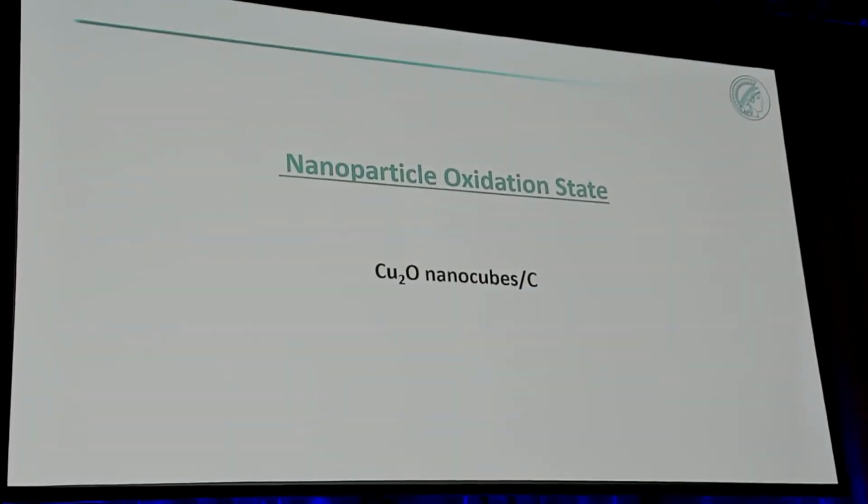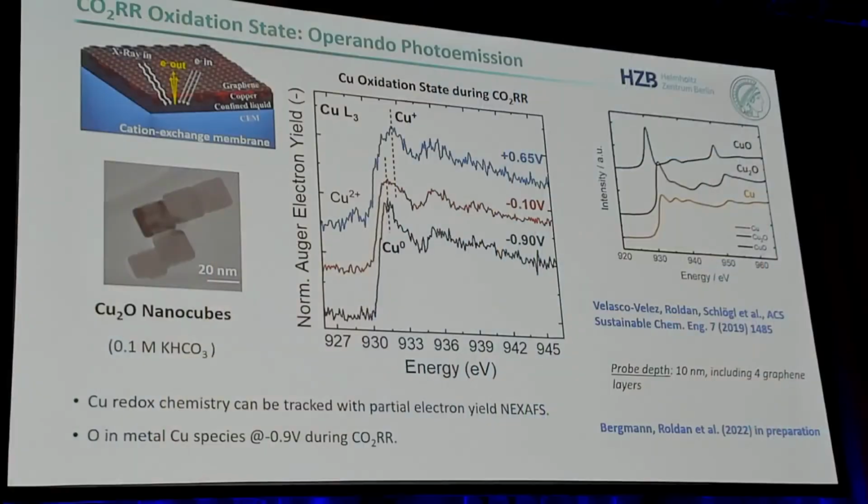So there is a long debate in the literature about whether the oxidation state matters, and for simple electroreduction, many people have been working on oxide-derived copper. And the question is whether there is any oxygen remaining in this material. What happens when you start with oxide-derived copper is that after it becomes reduced under reaction conditions, it becomes very rough, so you have all of these defect sites that I told you were key. To understand this, we spent about 4 years trying to design the right experiment under operando conditions to see if there is any oxygen left in this material.